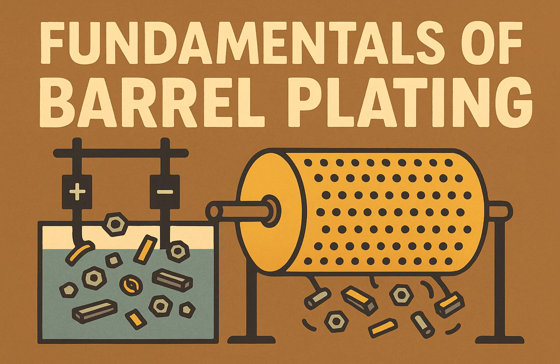So spotting out shows how crucial post-plating steps are, like rinsing and drying, especially when you have parts in bulk that might trap moisture or chemicals. Can't just dump them wet into a bin. Exactly. It highlights that the process isn't over until the parts are clean, dry, and stable. Better rinsing, sometimes even needing part redesign for better drainage, and a final warm water rinse, maybe with a neutral soap, followed by thorough drying, can minimize this.